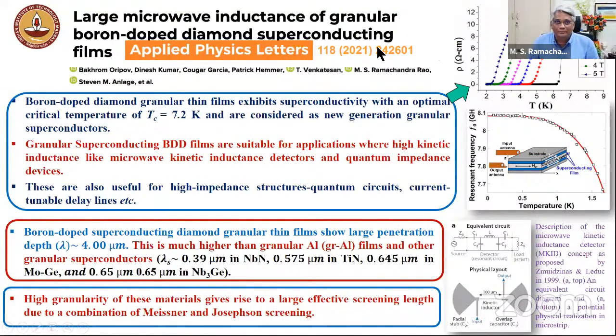This is one of the latest papers we got with a group from University of Maryland at College Park. This is very exciting because in the last 3 decades, lots of superconducting systems have been tried for many quantum impedance device applications that are used in microwave circuitry. But the condition is, even though we have hundreds of superconductors available, you need superconductors that are granular. So for example, you have aluminum in the form of a granular superconductor that has been used, niobium nitride and titanium nitride. But then it is turning out that boron-doped diamond, in which we see superconductivity, shows the largest microwave